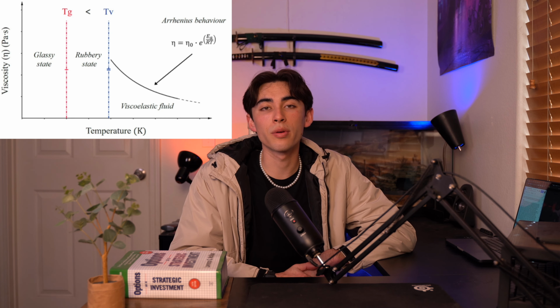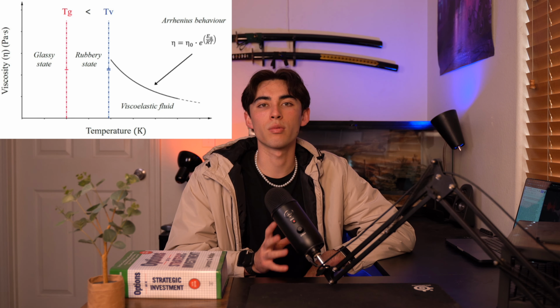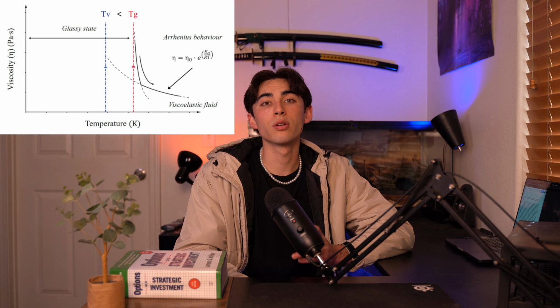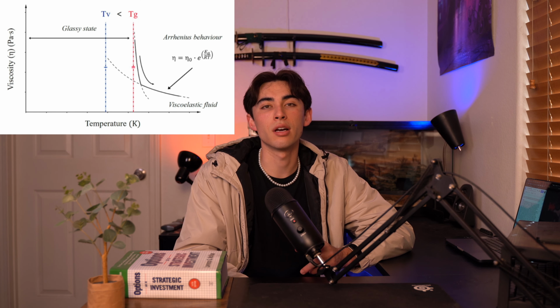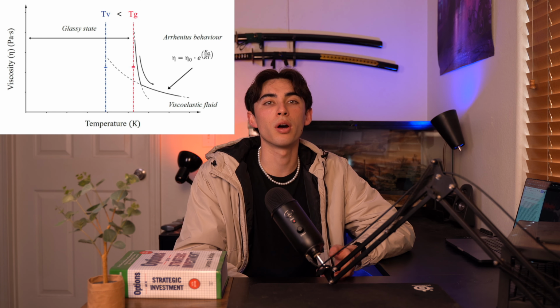When TG is lower than TV, both glassy and rubbery states are identified. However, when TG is greater than TV, a glassy state is present until bond exchange becomes dominant and the Vitrimer behaves like a viscoelastic fluid.